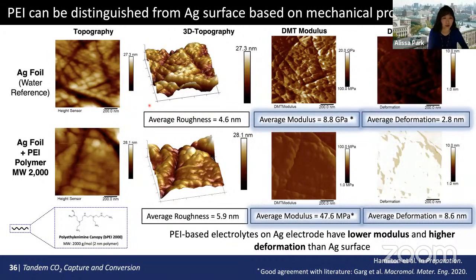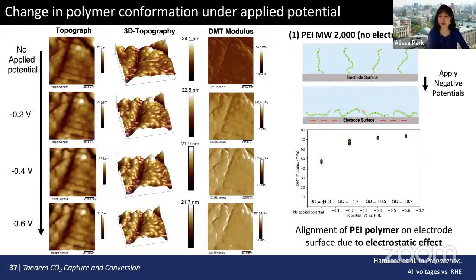So here, let's look at the no applied potential with PEI we started with, and as we hypothesized, more likely PEI gets adsorbed onto the surface of the electrode, and because it's charged, it will have a certain conformation. And if we apply the potential, what we found out was these polymers get collapsed onto the surface of this electrode, which means that with and without the potential, you have very different transport behavior on the surface, and interaction between this polymer in electrolyte and electrode surface will be very different.